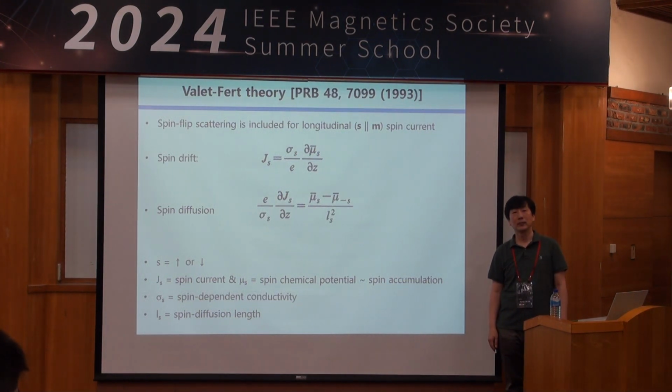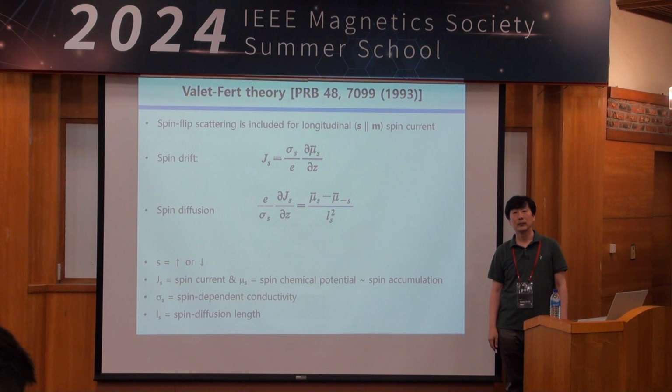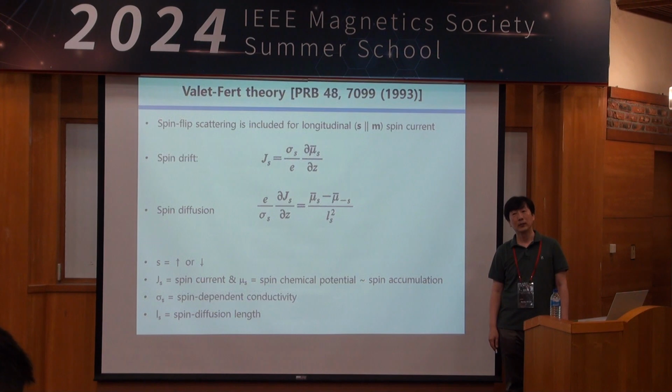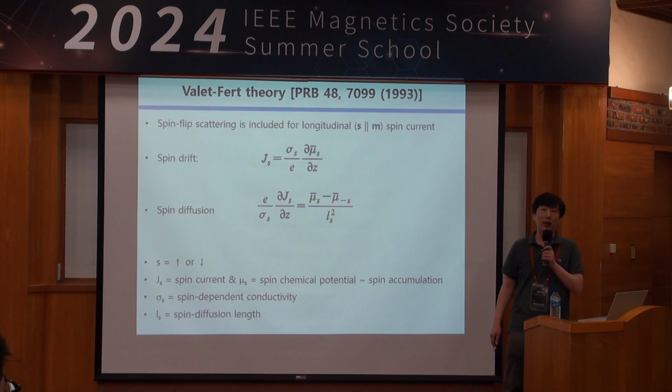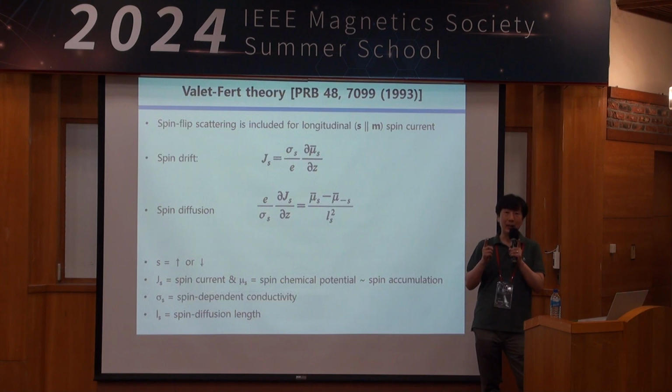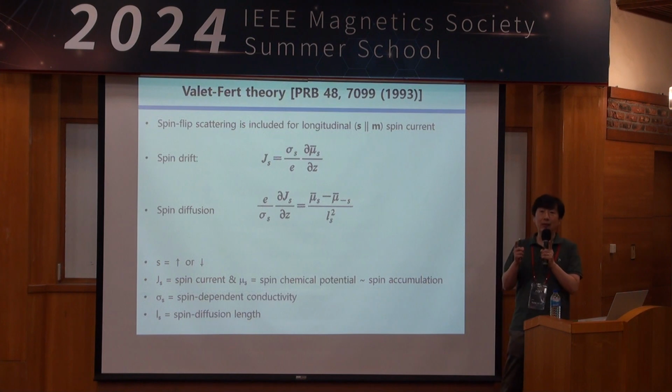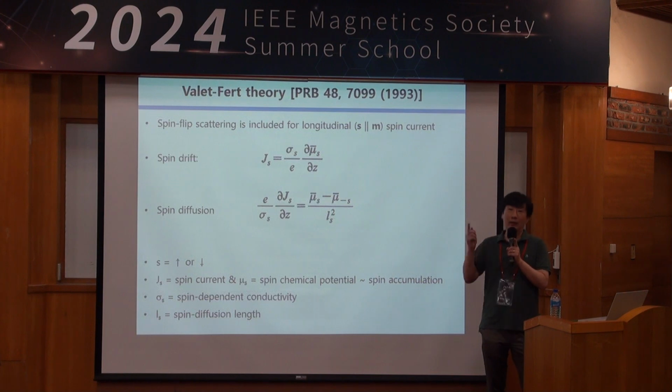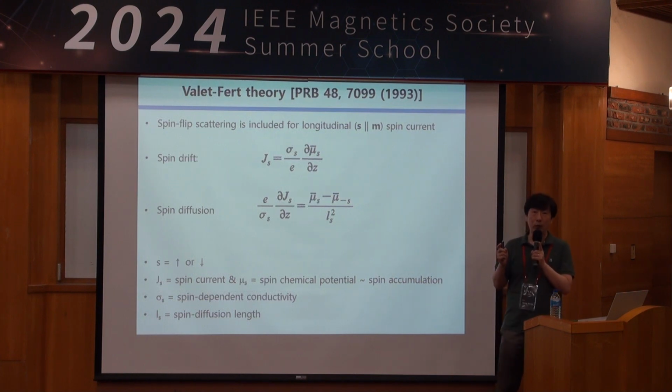You said we couldn't use a continuum approximation for antiferromagnets or ferrimagnets, but why is that the case? I didn't really get why. If you want to use the continuum approximation, it means that within a unit cell you have uniform magnetization. However, for an antiferromagnet, the equilibrium magnetization is 0, and it becomes some very small number during the dynamics, but it is non-uniform within the cell. So there is no way to calculate the antiferromagnetic dynamics using the continuum model.